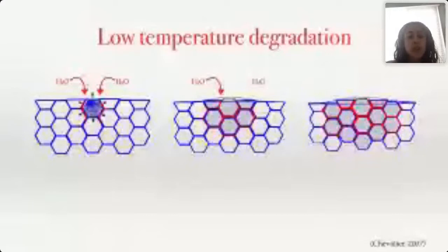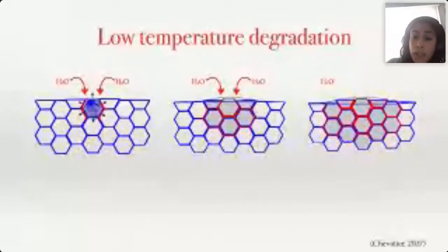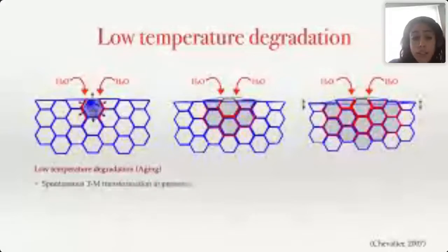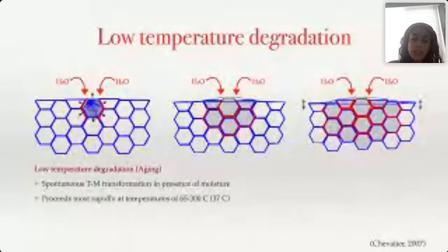The last property of this material is that when there is moisture around, that TM transformation can form again. So the grains also transform in presence of microcracks and water or moisture, and that leads to increasing grain sizes, surface uplift, and maybe delamination of these surface grains. But we don't need to be too concerned because it was thought to occur at low temperatures, 65 to 300 degrees Celsius.